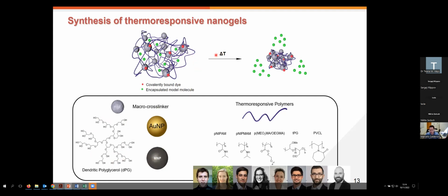What we pursued here was a response in the nanogel, going from a swollen system, like imagine a sponge completely soaked with water or with molecules. And then when we increase the temperature, we press this sponge, and the sponge releases the molecules that are inside. These molecules are the cargo molecules we have, but also, and very importantly, water. So we should keep in mind that our material will release water. And this is especially important in topical drug delivery, because hydration of the skin is also one methodology of penetration enhancement.